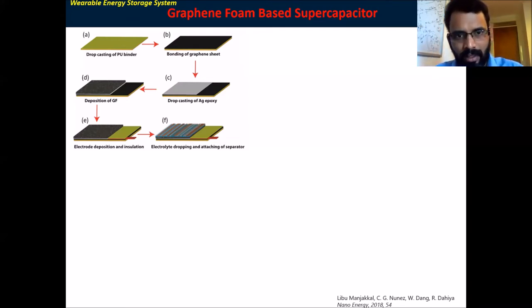So I need to attach a graphene foam on top of a graphene sheet. Traditionally, the work is mainly done by preparing a graphene foam using an insulative epoxy. That increases the resistance. To solve that issue, I used a normal silver epoxy. It's a conductive epoxy. Then a freestanding graphene foam. There is no insulative material inside.